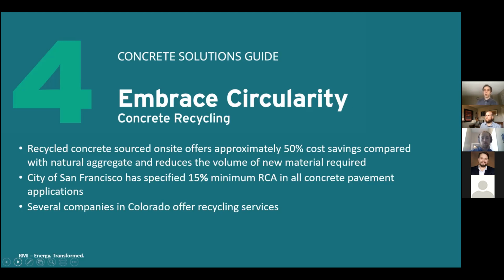It is important to note on concrete recycling that from an emissions perspective, it needs to be used in non-structural applications in order to have an emissions benefit. Because of the variable nature of the material and the size and grading and potential for mortar to be left on the material as well, it can have a negative impact on the strength of a concrete mix. And if that's the case, any additional cement that's used in the mix will offset any benefit associated with the emissions reduction of using recycled concrete because it is relatively small.